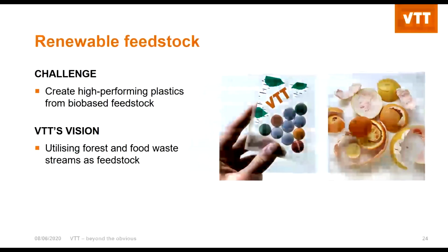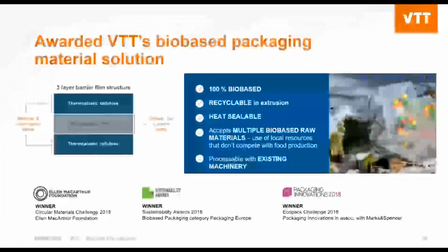One really nice example is actually our awarded bio-based packaging solution, where we have coupled two cellulose-based films together. So we have this thermoplastic cellulose and nanocellulose film that have complementary properties. The thermoplastic cellulose provides the moisture and water vapor barrier properties, and then the nanocellulose film gives the oxygen, gas, and grease barrier properties. The solution is 100% bio-based.